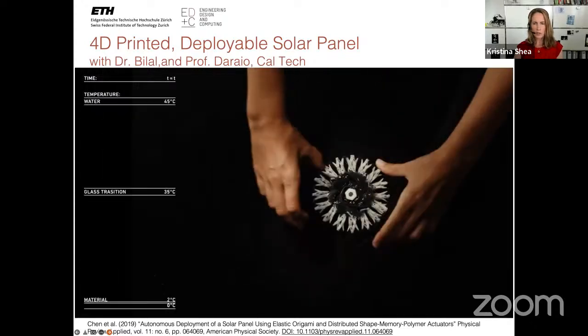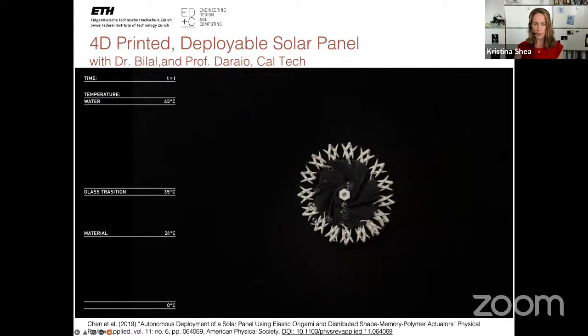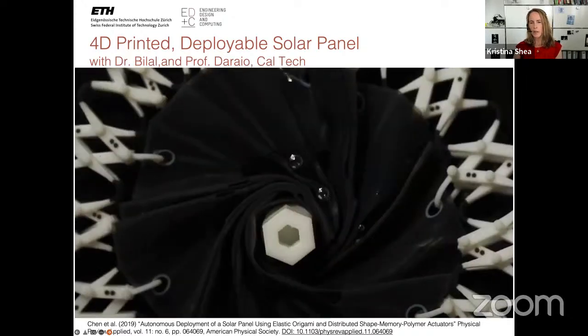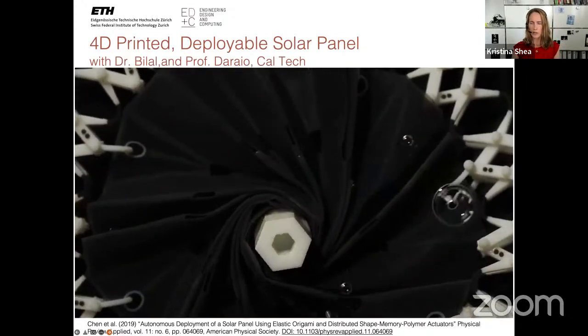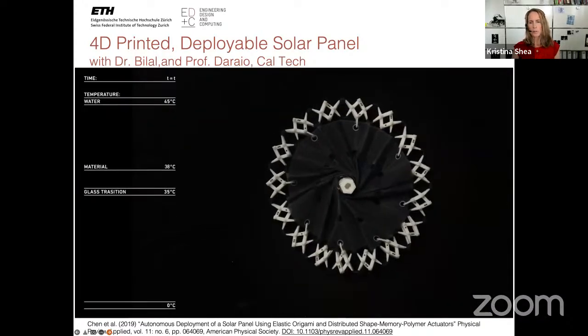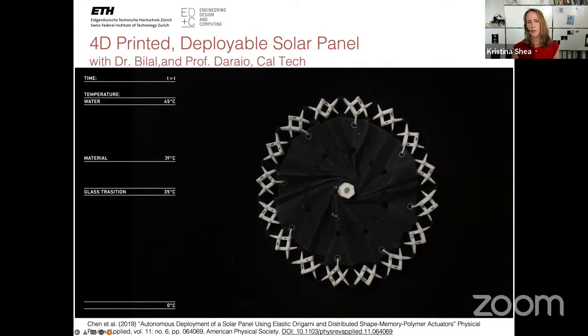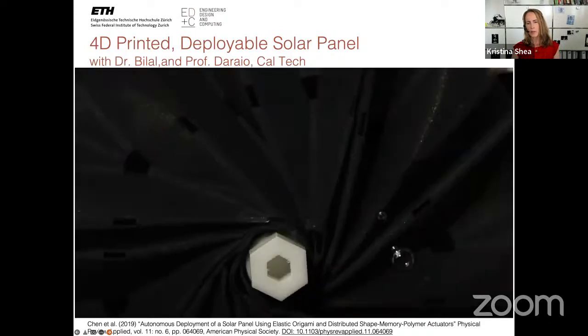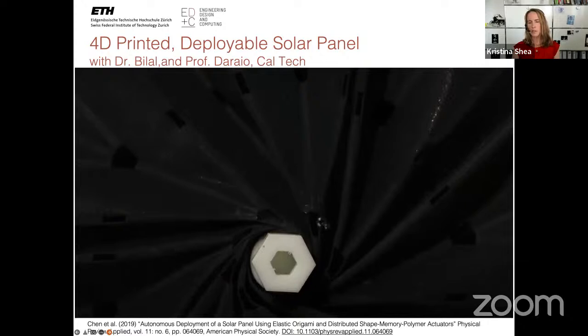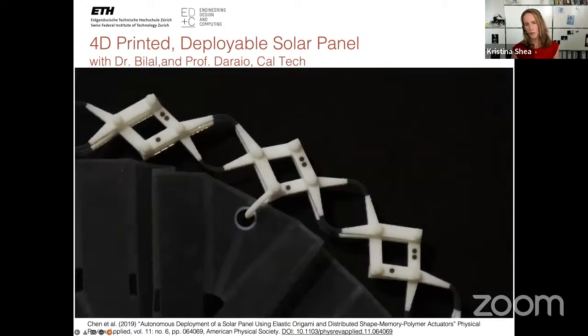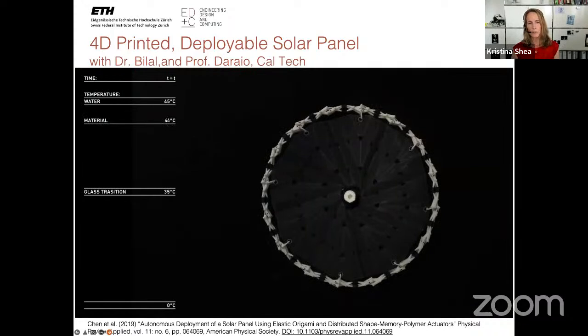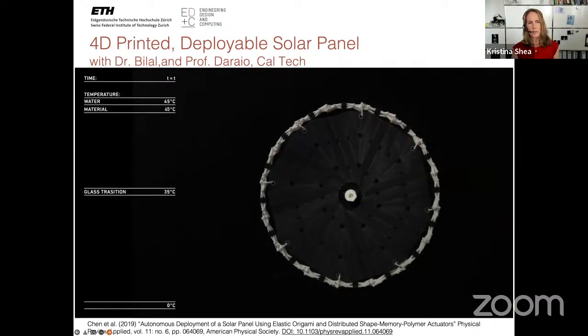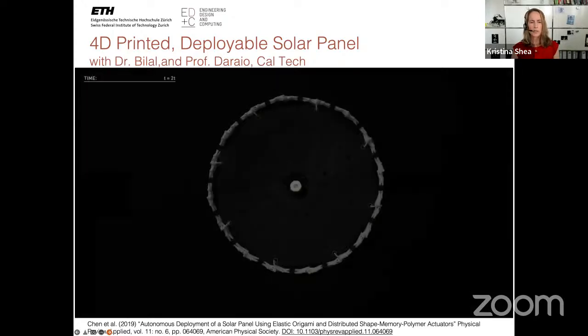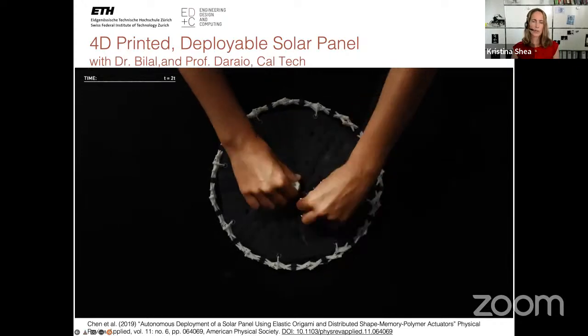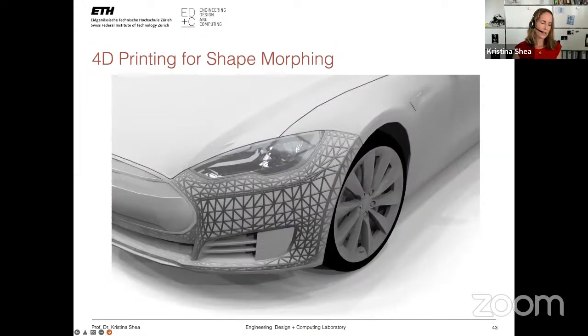So it's again this material programming aspect, and then it will expand out, and it's using a scissor mechanism on the outside, also with some shape memory polymers. So it expands out in less than a minute. So it expands 10 times in less than a minute. There you can see the joints and the rigid and soft materials next to each other. And here it's going up to a temperature of about 45 degrees. And so it's using the temperature to actuate. There are no single individual actuators on that.